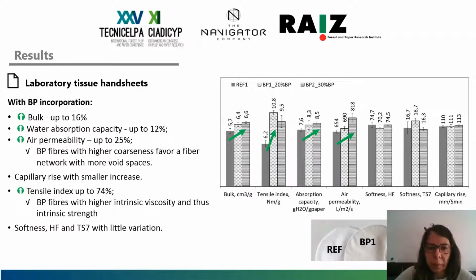Afterwards, the bark pulp produced, as I mentioned before, was used to prepare different formulations, and these formulations were used to prepare laboratory tissue handsheets. The results of the analysis of the tissue handsheets revealed that the incorporation of bark pulp yielded an increase on bulk, an increase on water absorption capacity, and also an increase of air permeability.